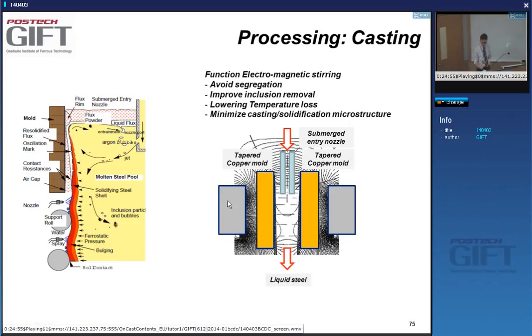First of all, let's have a look at what the functions are of these electromagnetic stirrers. You can influence segregation. You can improve inclusion removal. You can decrease temperature loss or inhomogeneity, and minimize a very pronounced solidification microstructure. So these EMSs can be put at different places during the casting.